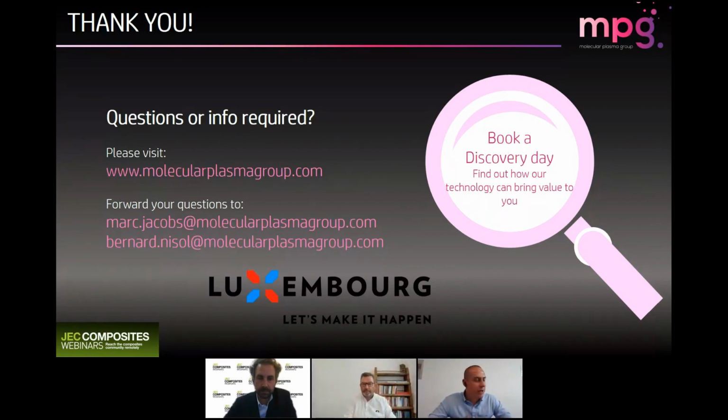To me, that's the only way it's possible, and I think it is possible, but the customers we're working with cannot do that, simply because the PP may be ultra thin, for example, and even with the Corona, at some point you're going to damage the polymer. Right? So the customers we're working with have this problem of storage, open time. They treat with Corona, and yet after days or maybe 1 or 2 weeks, they have lost it.